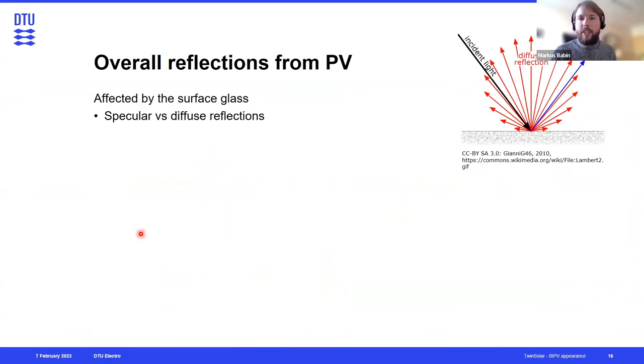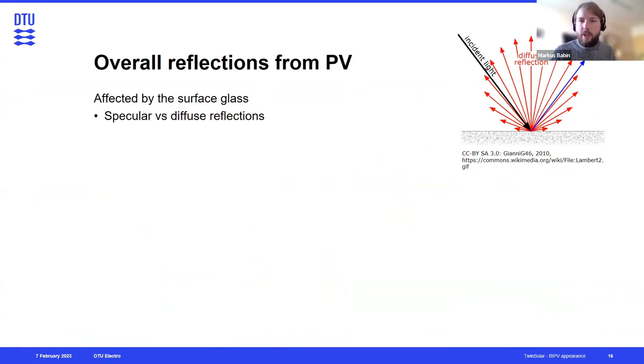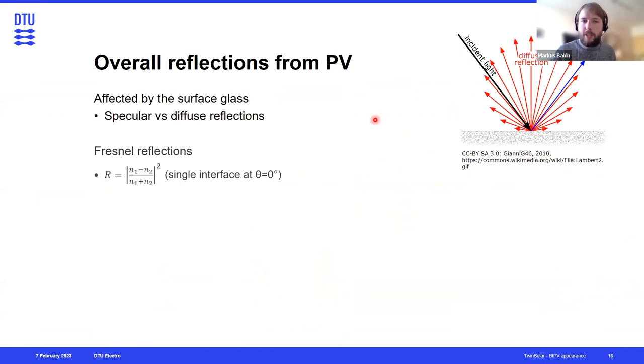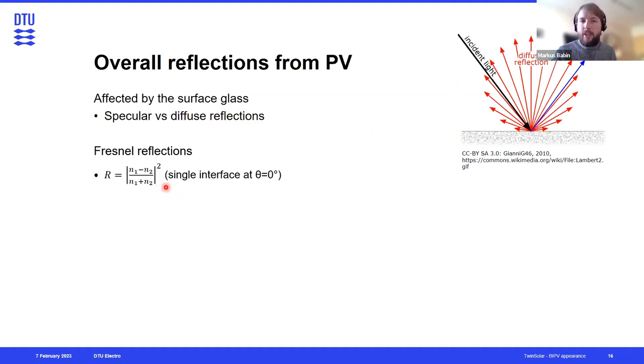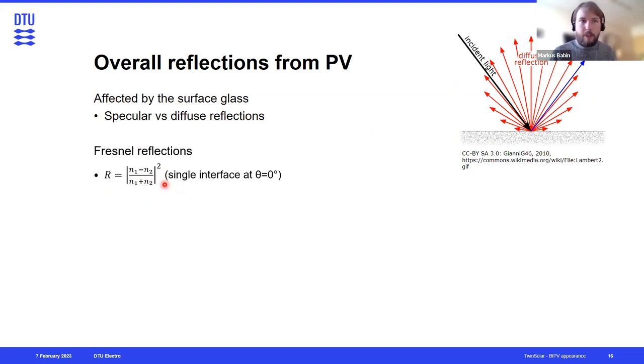Before going through all these technologies, I wanted to quickly mention that reflections from PV modules do not only depend on whether we use pigments or structural colors, but also on the surface glass. Whenever we have a surface, we get specular or mirror-like reflections from flat surfaces, or diffuse reflections from rough surfaces. Whenever we change material interfaces — going from air to glass — we will see some amount of reflection, following the so-called Fresnel reflections, which correlate with the refractive indices between the two materials. Going from air (refractive index ~1) to glass (refractive index ~1.5), we will see about 5% reflections.